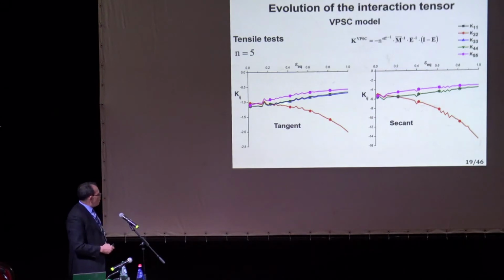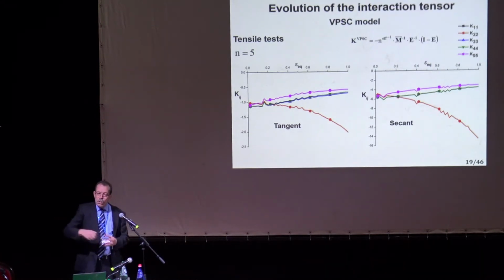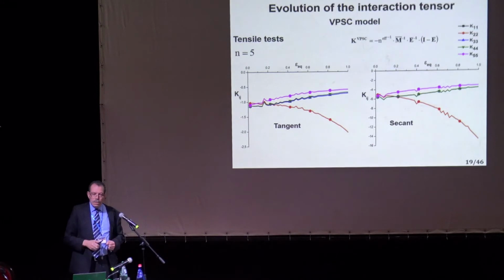So what you should notice is the values again. For the tangent, the values are of the order of 1. Here the values are 6 times higher, which means that the interactions with the secant modulus are higher. So it's not surprising that I will show you the results with the secant modulus. We got results close to the upper bound.